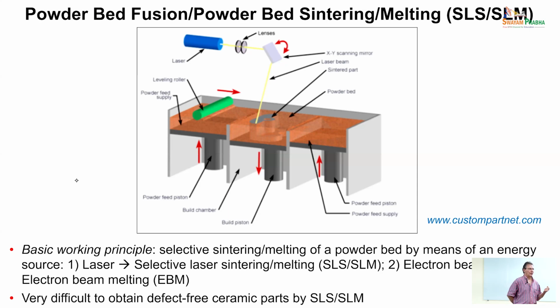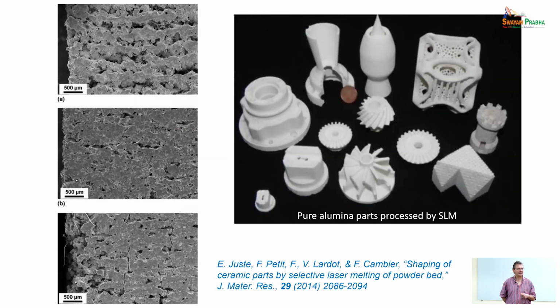For ceramics specifically, this technology would be very nice because it would allow you to obtain an already sintered part after shaping. There are some difficulties because it is very difficult to obtain parts that do not contain a significant amount of defects. These are old data. People are doing better things now. You can see some nice capabilities in terms of shaping, but if you then look at the microstructure, you can see that there are a lot of localized voids, and especially cracking.